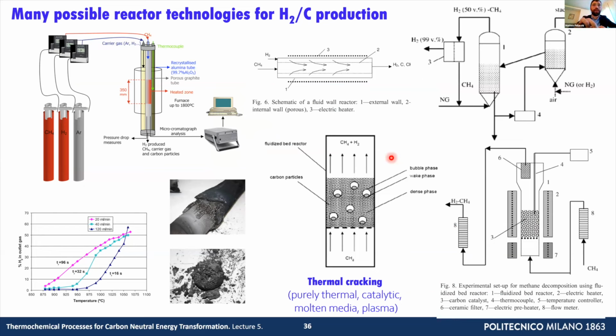So you can think about a conventional flow reactor where you feed methane, this is cracked in a heated zone, and you produce hydrogen and carbon. You can think about a fluid wall reactor, where you want to avoid deposition at the wall that would cause clogging, so you have an internal porous wall that allows diffusion of hydrogen from the wall to the inside, but does not allow diffusion of the particulate matter you're forming to the wall, causing reactor clogging. Then you have other types like the fluidized bed reactor, which is a more or less conventional configuration.